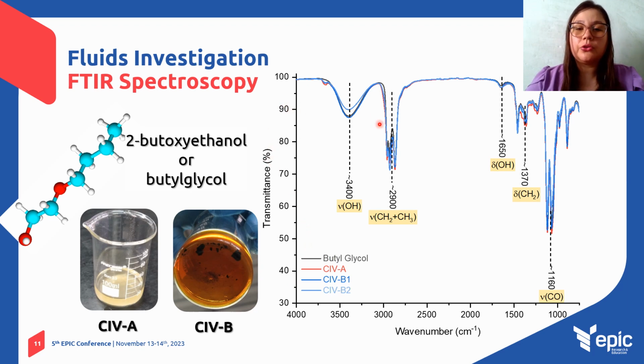Thus, it is also possible to conclude from this infrared spectrum that there are no significant absorption bands that might indicate chemical degradation of this butylglycol, indicating to us that this glycol is stable at the injection conditions.